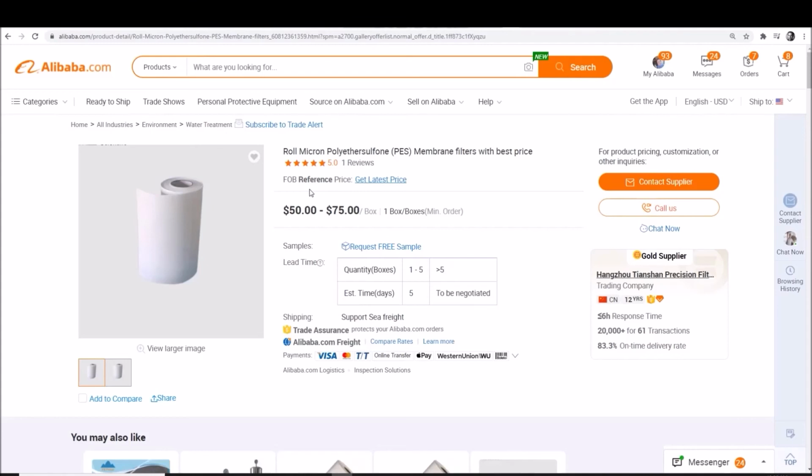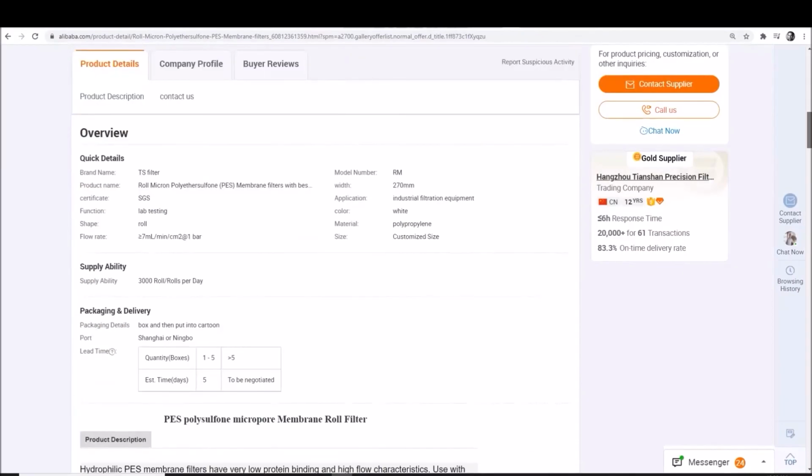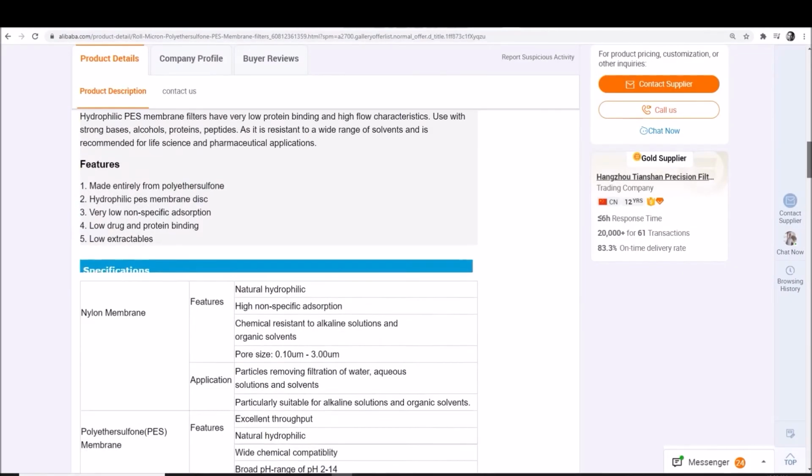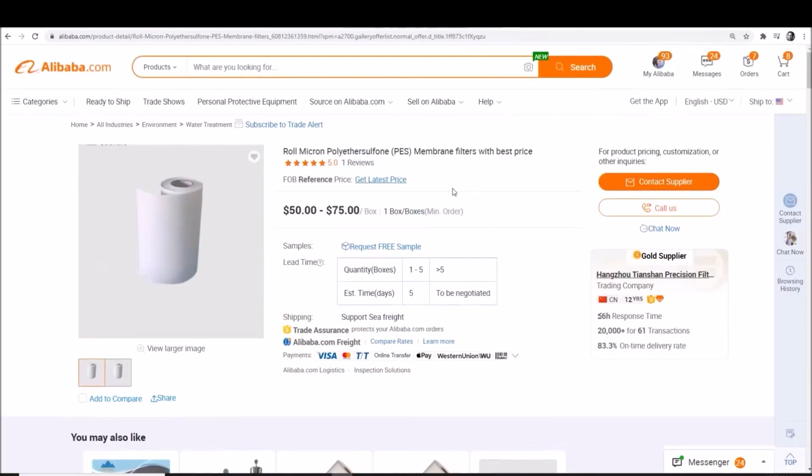And so people say, well, the materials are not ideal. They're close to ideal. Maybe Zirfon is ultimately ideal, but it's going to cost 4 or 5 times more. I haven't gotten a quote for it, but this cost me $10 per square meter for a 200 micrometer. So 200 micrometer, it was $10 per square meter, which is very cheap. I do not expect the Zirfon to be even in that ballpark. It's probably over $100 per square meter.